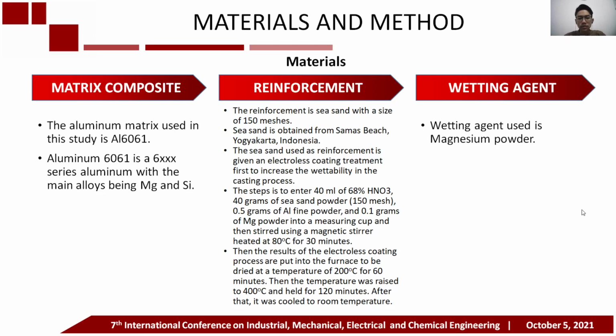Then, the results of the electroless coating process are put into the furnace to be dried at a temperature of 200 degrees Celsius for 60 minutes. Then the temperature was raised to 400 degrees Celsius and held for 120 minutes. After that, it was cooled to room temperature. And the wetting agent used is magnesium powder.